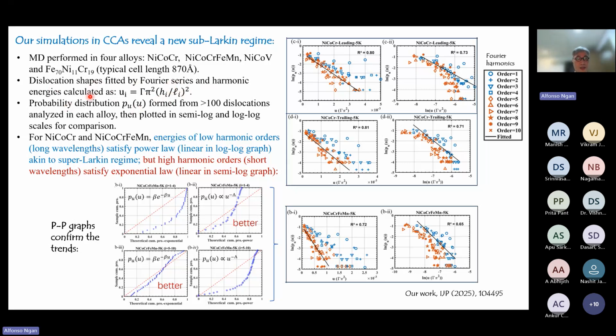And then with enough data, we can generate a probability distribution. So typically, we'll be using 100 dislocations from 100 simulation cells, and analyze their distribution. In all these plots, for the same group of data, we plot the results in semi-log on the left-hand side, as well as double log on the right-hand side. Typically for each alloy system and either the leading or trailing partial, we will be looking at the Fourier harmonics from 1 to 8 or 10, okay? They are represented by different symbols.